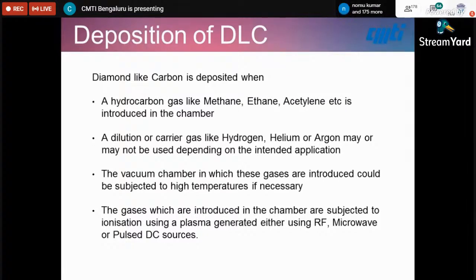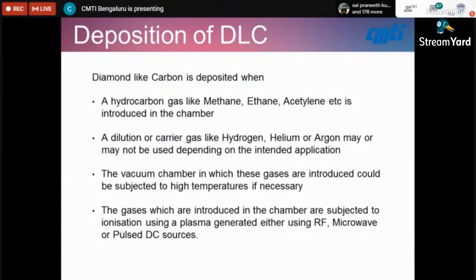What we would do is combine these both together in the chamber and then try depositing DLC. You have the vacuum chamber in which you let in these gases. You can subject it to 200 degrees or 300 degrees, whichever temperature you like, and then use plasma using RF, microwave or pulse DC. Then you would ionize these gases and start depositing. So is it as easy as I say? Yes, it is extremely easy to do that. However, you have to get your hydrocarbon to dilution gas ratios quite correct. These ratios depend on the type of system you have, the size of the system, and what pressure it can hold. It's quite simple to deposit DLC.